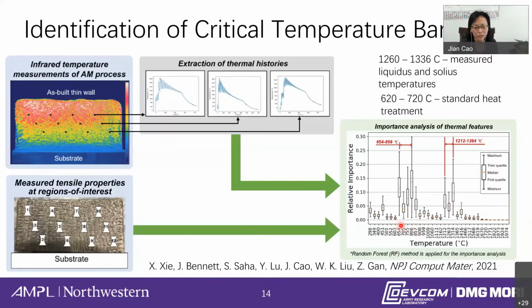So it's interesting in the sense that we know from previous studies that the solidification range is very critical, certainly when you think about the grain structure as well as the porosity buildup. But the other interesting thing is this zone that you spend at the lower temperature range, which actually corresponds to the material microstructure evolution as well.